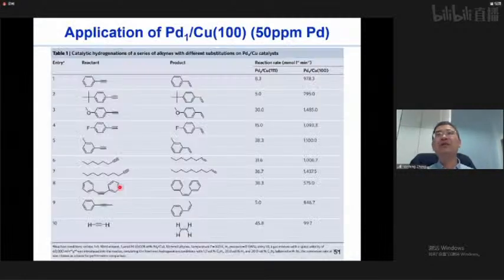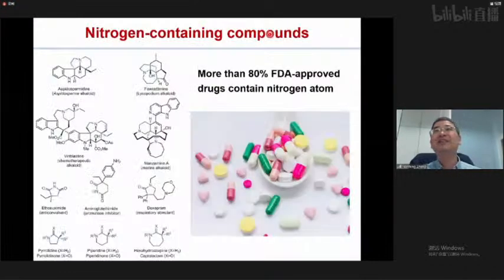Okay, so with this, basically, we found that it's possible to really decrease the loading of the palladium down to 50 ppm. So this is quite interesting, right? So we can lower down the loading of this palladium with a high price and replace it by copper.